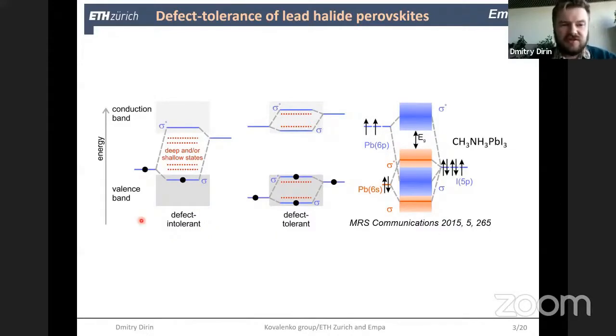So in conventional semiconductors, the bottom of the conduction band and the top of the valence band are formed by antibonding and bonding orbitals, respectively. And typically, all intrinsic defects, related for example to dangling bonds, interstitial atoms or vacancies, will create deep or shallow states within the band gap. This means that, for example, dangling bonds on the surface of a conventional semiconductor will create traps. And for this material, it is unlikely that it will exhibit bright photoluminescence at room temperature.